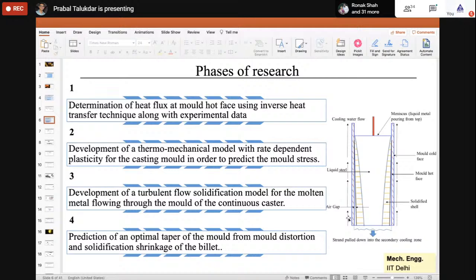As I told you before, it's always good to decouple or make your problem a little smaller so that it can be done effectively. So in the first phase of research, we tried to find out the interfacial heat flux between the mold and the billet. At the inner surface of the mold, the red color strip here is the mold. The outside is called the cold face of the mold, and the inside face is called the hot face. On that hot face, we try to find out the heat flux. What is the heat flux there?